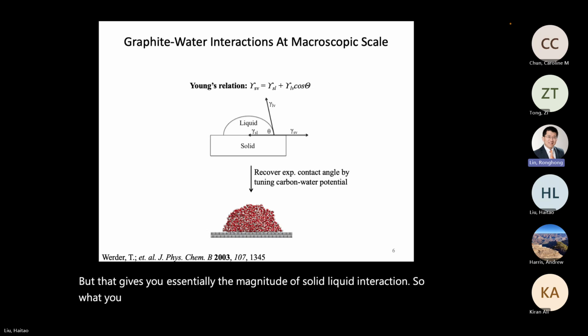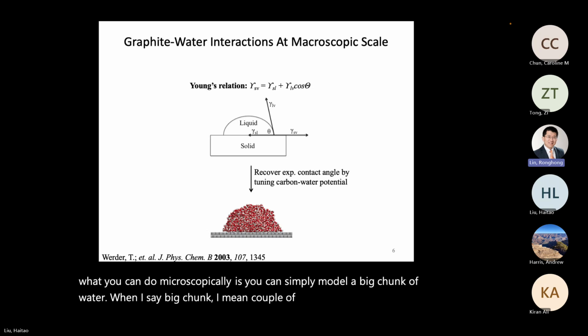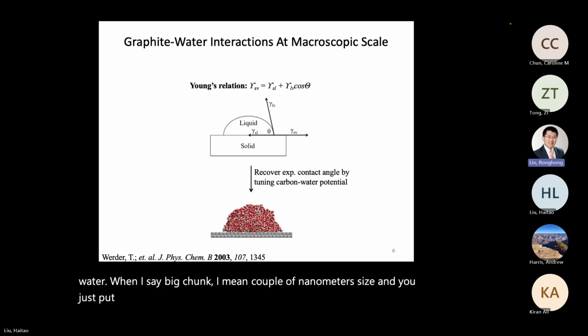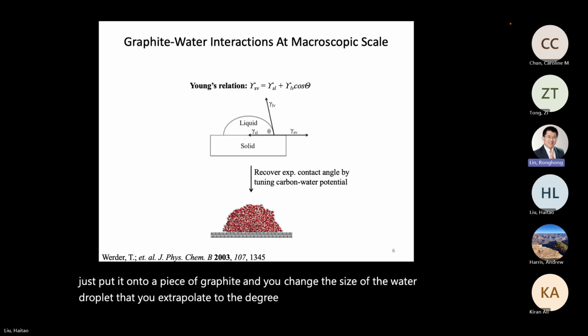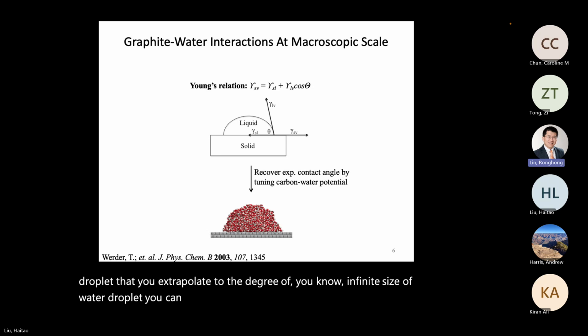So what you can do microscopically is you can simply model a big chunk of water. When I say big chunk, I mean a couple of nanometers in size. Okay, and you just put it onto a piece of graphite and you change the size of the water droplet and you extrapolate to the limit of infinite size of water droplet. You can get the water contact angle.